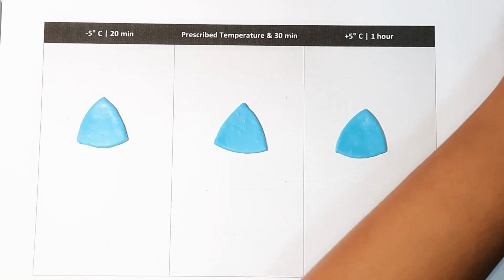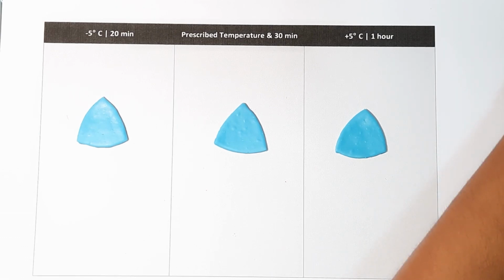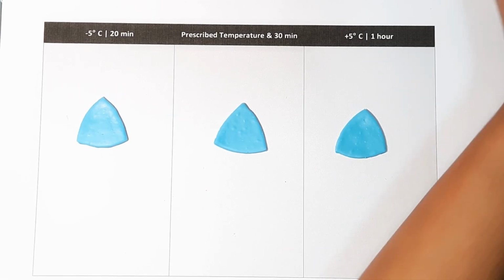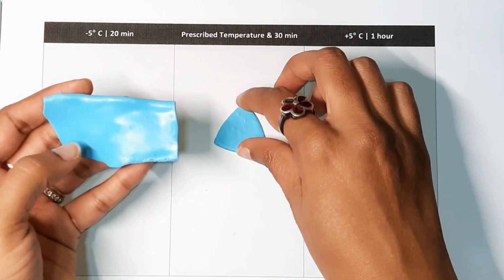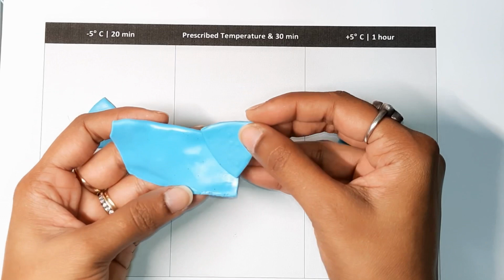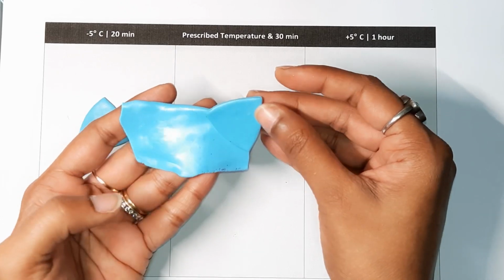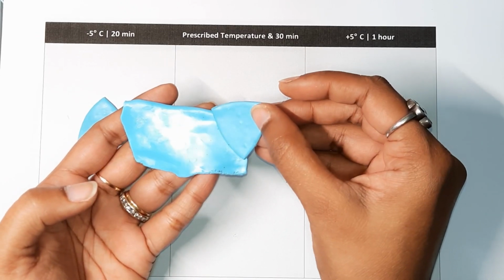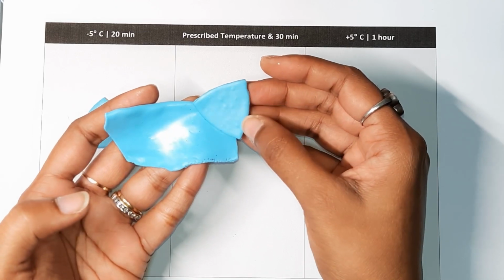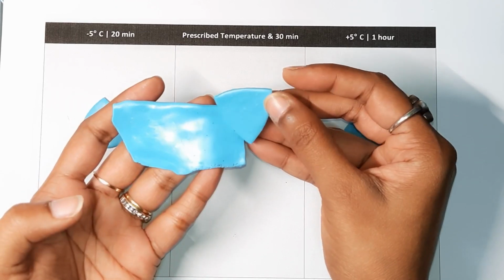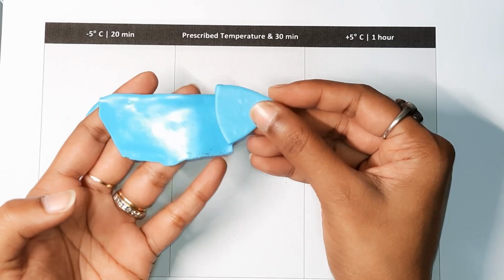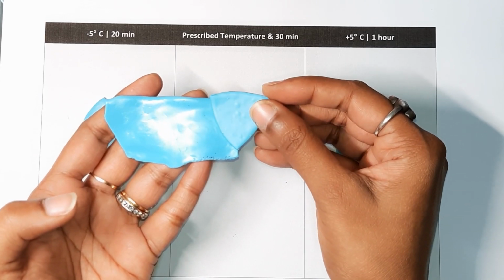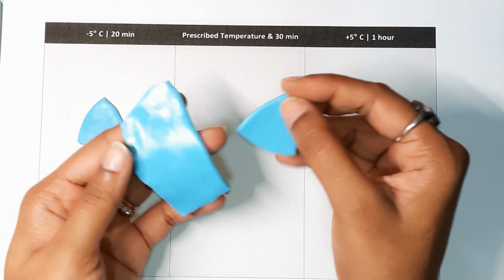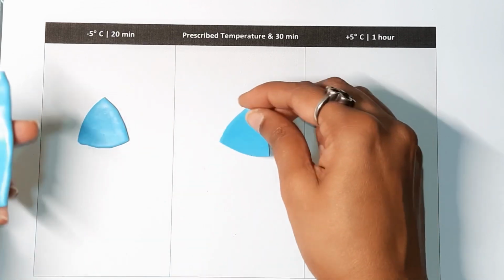Let's look at the color variation in this particular clay. I'll show you the original color and the variation from that original color. So this is the original color of the clay and the baked version at the prescribed temperature plus time. There's no difference in color, if you can see that. Absolutely no difference. But if you look closely, there are visible bubbles on the surface. My heart is really broken looking at that. But no darkening of the pigment and absolutely no translucency.